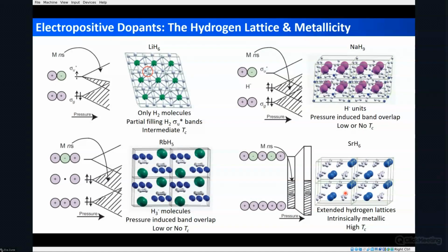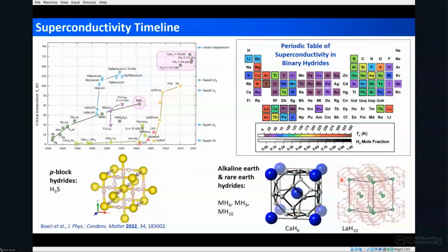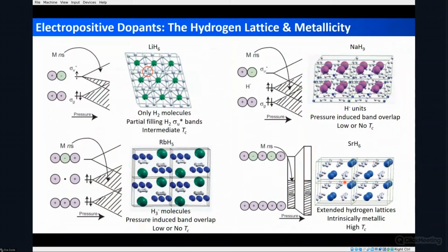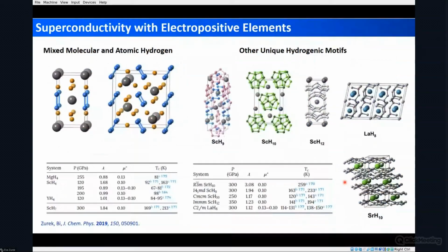So if you have a system with a 2D plane or with a 3D cage, like in these clathrate materials, the number of bonds that can undergo electron-phonon coupling is going to increase, and that increases the TC. So this goes into the review article that we have written, where we have surveyed a number of the different cases with high TCs and looked at the trends that are found in their TCs.